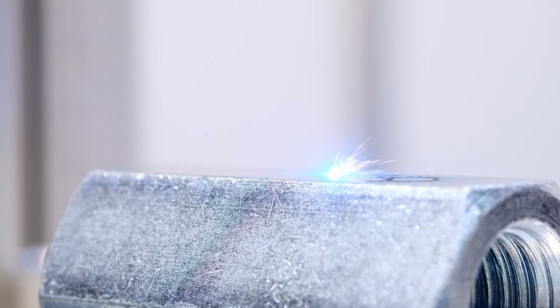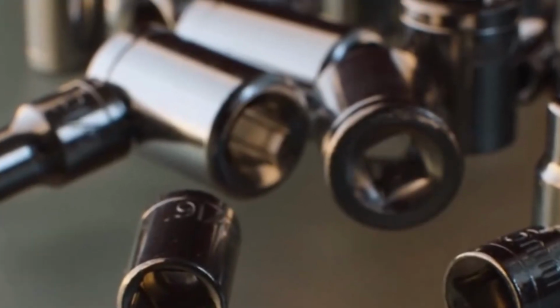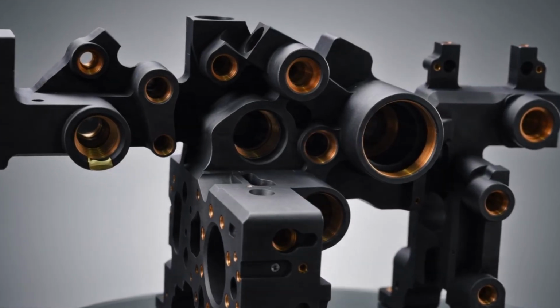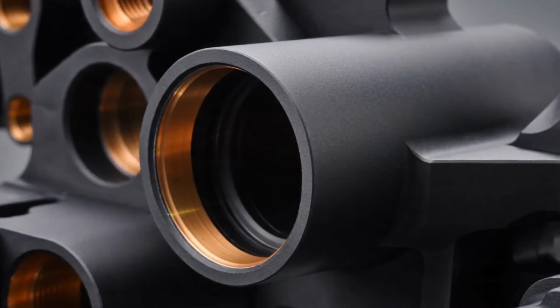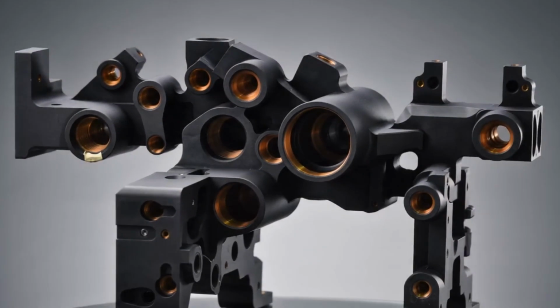For areas without strict positional accuracy requirements, localized laser engraving was used to remove the anodized coating. Finally, all areas where the anodized layer was removed underwent chromate treatment to achieve both corrosion protection and electrical conductivity. Final results: anodized layer thickness met the requirements, resistance in conductive area around the flow channel ends was within specification, and the positional accuracy of critical holes remained within tolerance.